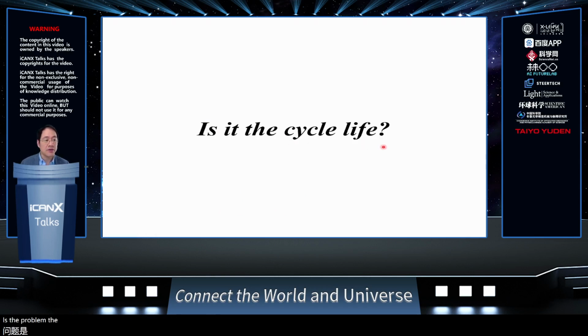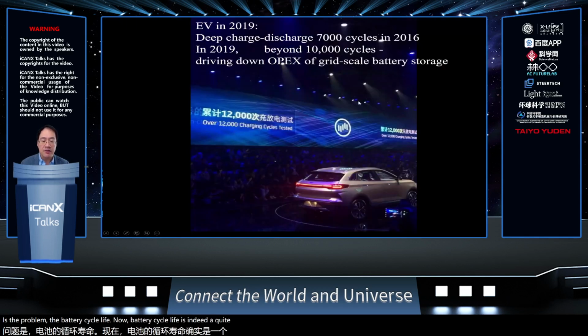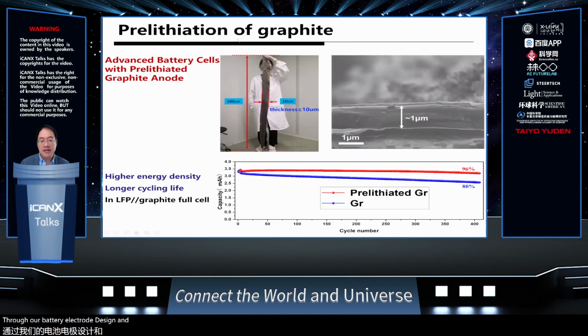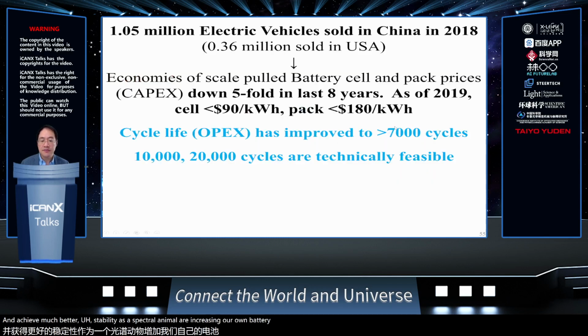Is the problem the battery cycle life? Now, battery cycle life is indeed quite important. However, because of the development in the electric vehicle industry, the battery cycle life has greatly improved through electrolyte optimization, which I will show a bit of our research on later, through better electrode design, and technologies like pre-lithiation. So in this demonstration, we can have graphite electrodes pre-lithiated by contacting with a metallic lithium foil and achieve much better stability as a battery anode in the lithium-ion battery. And so even though battery cycle life is important, it is possible to hit a cycle life of 20,000 cycles, even with pretty deep charge-discharge cycles.